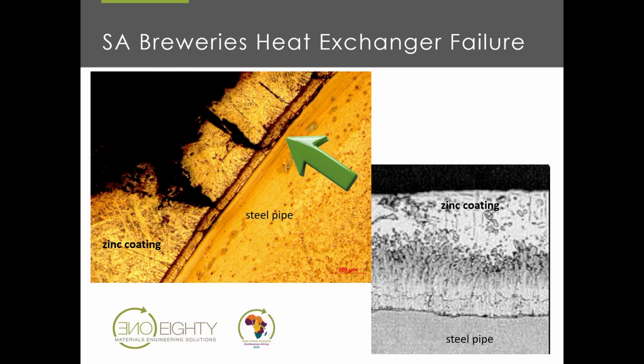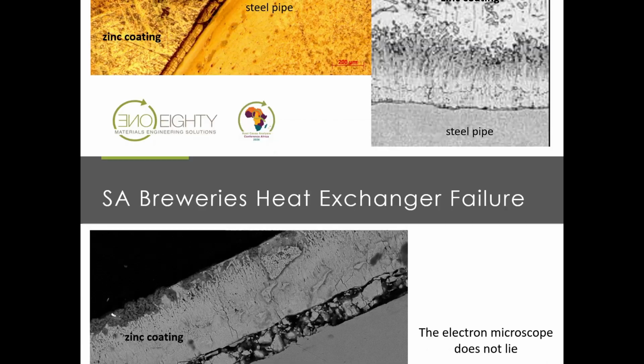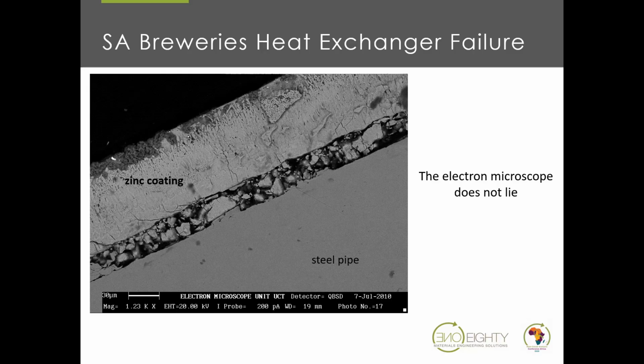But that we can see with the electron microscope, which does not lie. And it doesn't take sides either in these matters. So here is the steel pipe. Here's the zinc coating. And again, using the backscatter detector that gives us a compositional contrast, we can see the under-galvanizing rust. And there were many images like that.